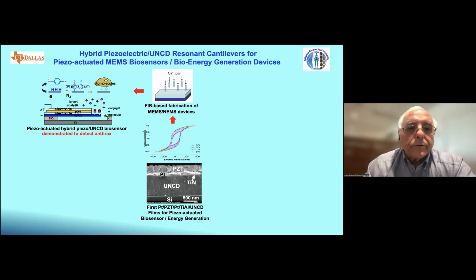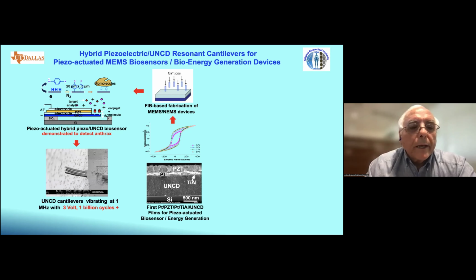So we demonstrated that we can grow a PZT film with top and bottom platinum electrodes on the UNCD surface. We put a biomolecule here that can attract these molecules that are dangerous from animals. And we demonstrated that by applying 3 volts between the top and bottom electrode, we can then vibrate. And when the anthrax molecules are attached here, that is the detection for anthrax molecules.